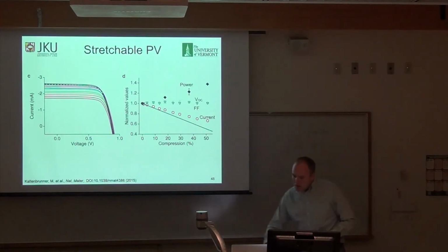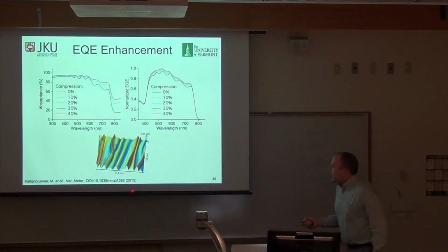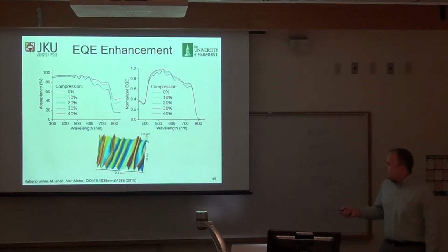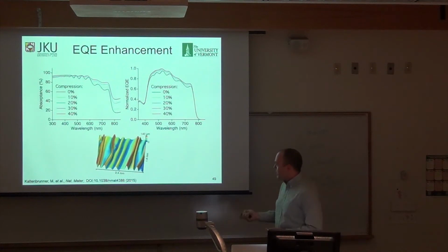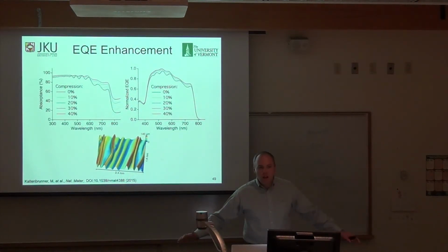If you look at this microstructure, when a ray is incident, there are multiple chances for the ray to reflect off of several of these valleys before it gets reflected back into space. So if the light is not absorbed, here it has more chance to be absorbed. You see that in the quantum efficiency here, where at higher compression you have a higher overall quantum efficiency. So it's essentially like taking a flat solar cell and making a pyramid structure on the front just by compressing it.